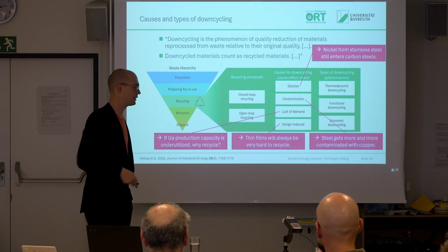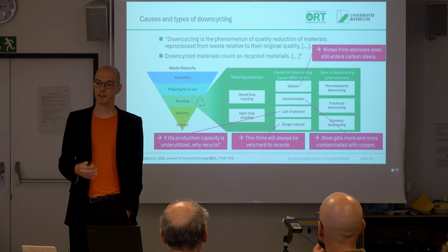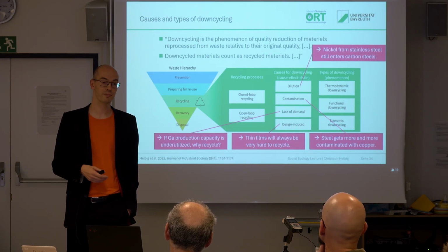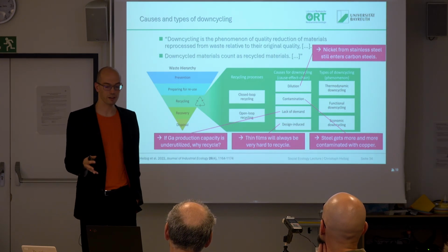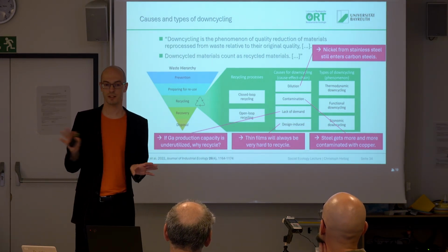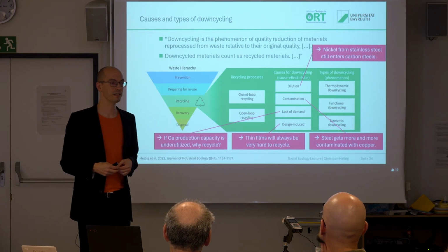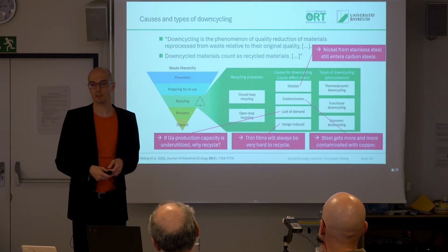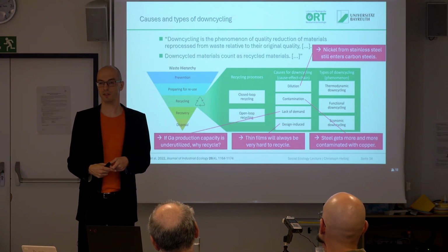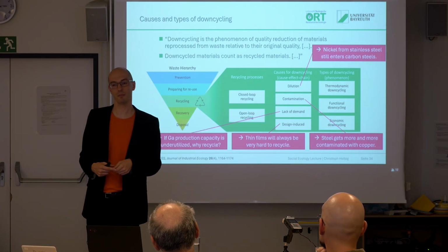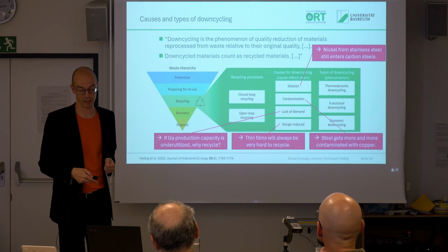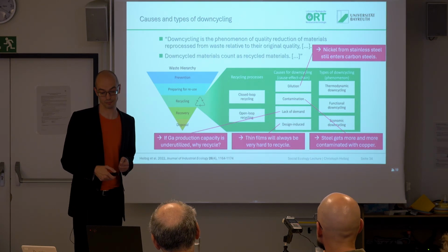And then the last one is design-induced. Well, sometimes thin films recycling will always be tricky. So indium, that's a big issue. Very often in your smartphones or your laptops for thin films, indium tin oxide, transparent conductive material. Well, you can't get indium back out from your smartphone. You will not recycle that. It's just so little of the material. That's not valuable, and that's thermodynamically really complicated. But that's the main application.